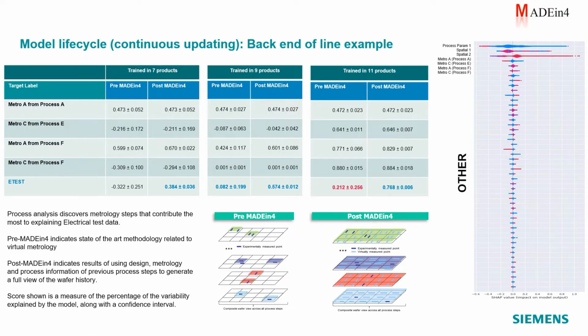One of the biggest questions about machine learning is, how do we know that we are improving our model? We can perform an analysis of the contributors. When we create a model that is trained on 7 products, we see that we are only able to explain about 40% or 38% of the variability. As we add 2 additional products, we are able to explain about 57% of the variability. And when we have 11 products, we are able to explain close to 77% of the variability.